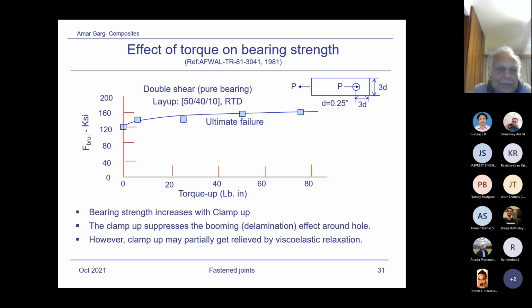The purpose of using the lower value is because we know composite joints do relax because they are viscoelastic materials. They relax with time. So the torque in 10 years of service of the aircraft may come down by 50% or 40%. So in order to account for that joint clamp up relaxation, the philosophy is to design the joint with the test data considered for the bearing stress allowable at around 50% of the clamp up.